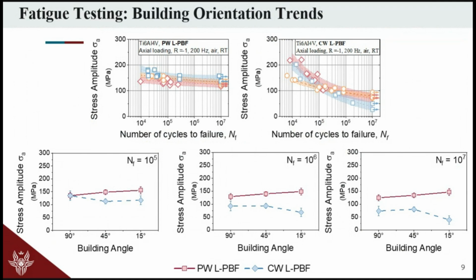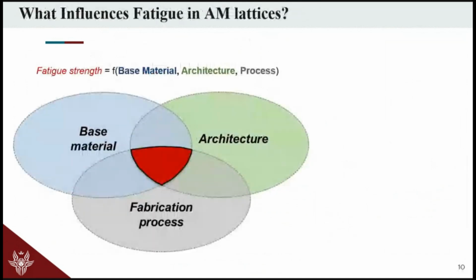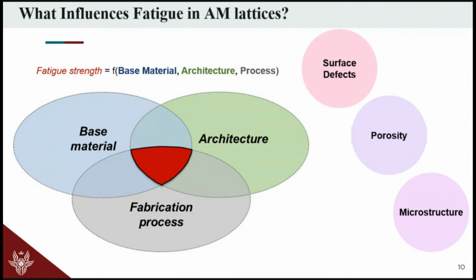So why this? Can we explain these trends? And in order to do this, usually when we talk about fatigue and fatigue strength, we consider a function of the base material, of the architecture, and of the fabrication process. But if the base material is the same and the architecture is the same, this suggests to us that the fabrication process is the key difference. And in particular, we are analyzing surface defects, porosity, and microstructure, which might be the driving phenomena which lead to